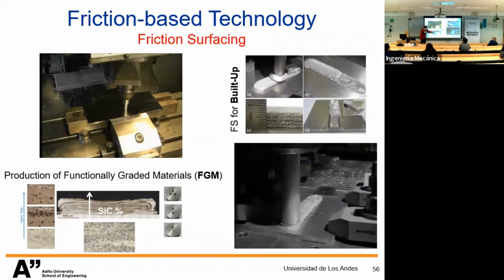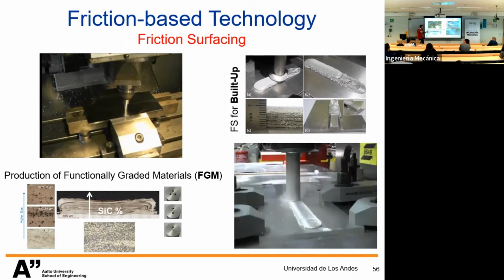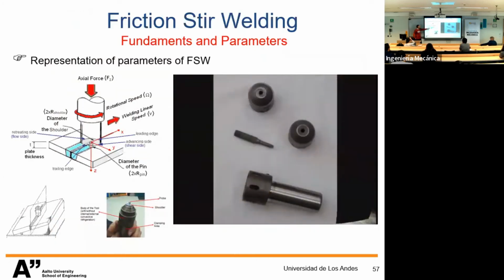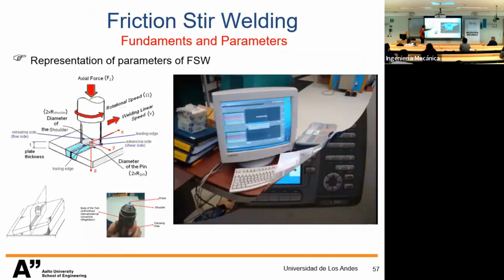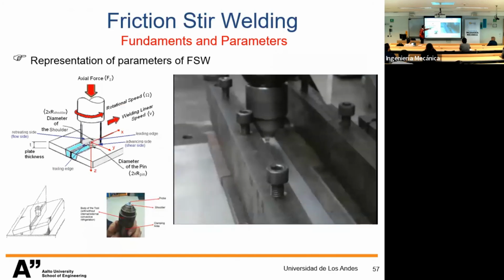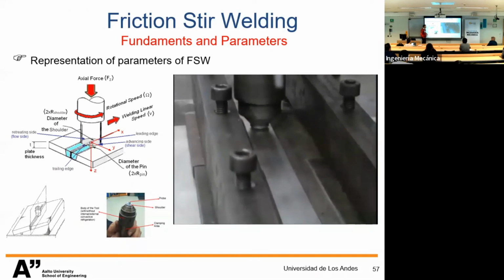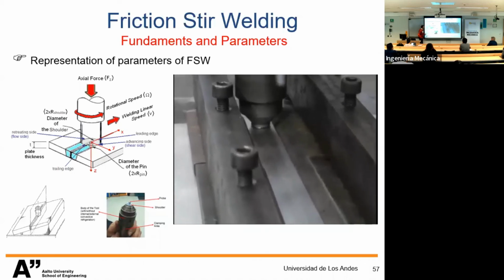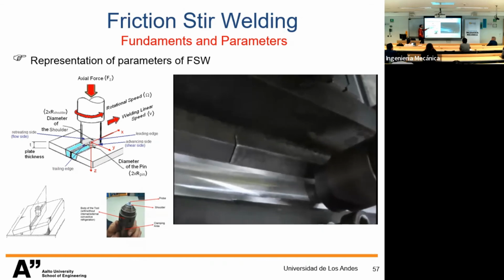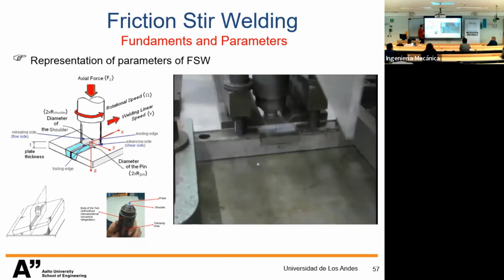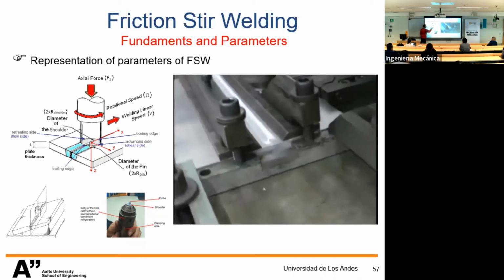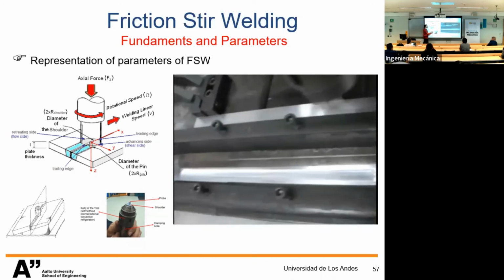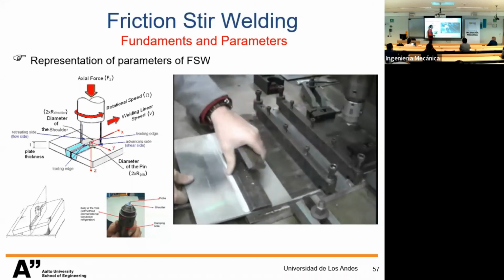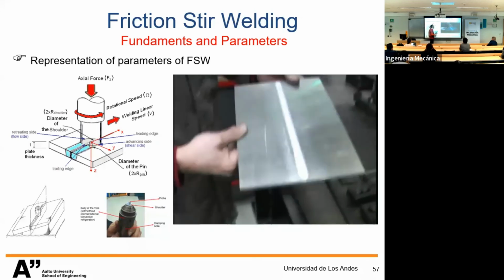And we can also produce functionally graded materials, FGMs. And we have friction stir welding, where the processed zone is encompassed by solid state cold material, a pin, and a shoulder, and then the probe does the mixing and stirring effect in the processed zone. So you will have a closed die system where the viscoplastic material has to undergo a significant amount of plastic deformation. The shoulder prevents the material from coming out of the processed zone, and the probe has to be resistant. The tool can take any path, and this brings the opportunity of joining materials. And aluminum alloys in general, they are thermomechanical processes.